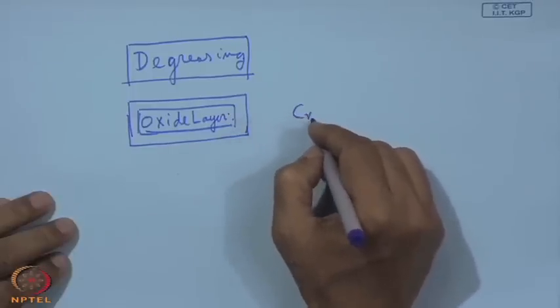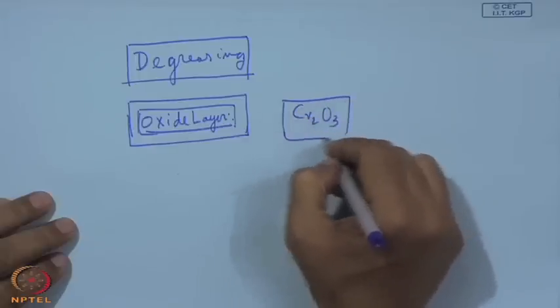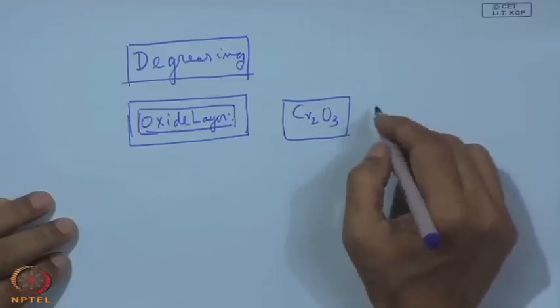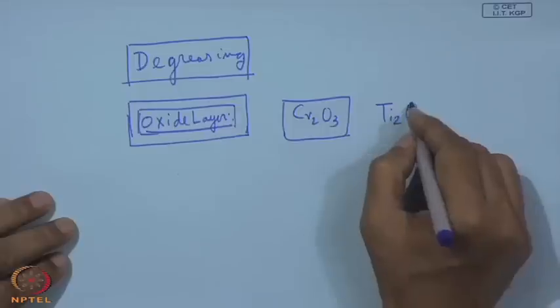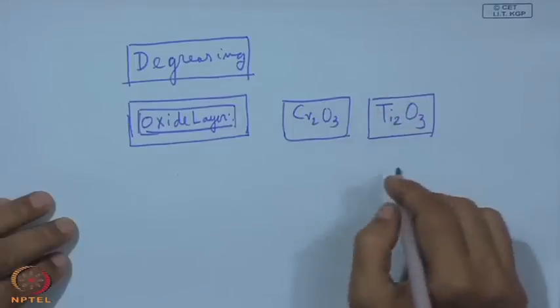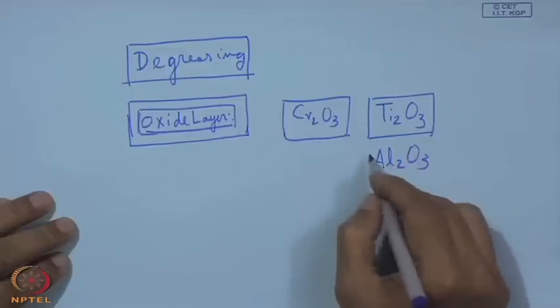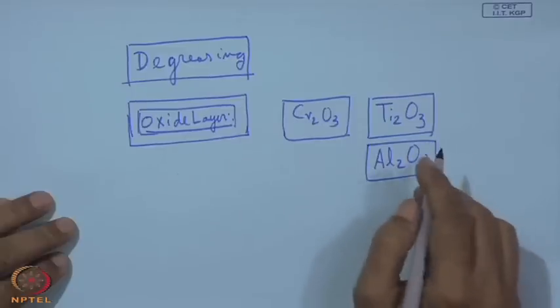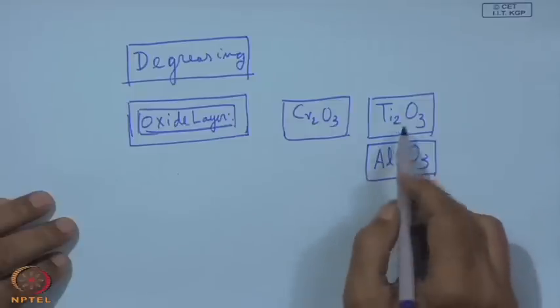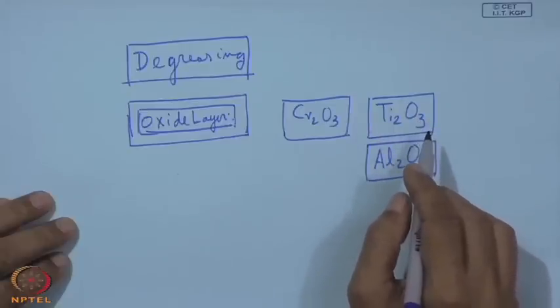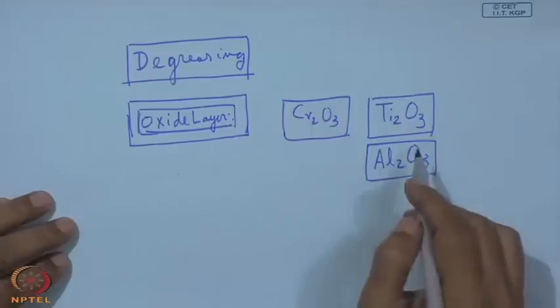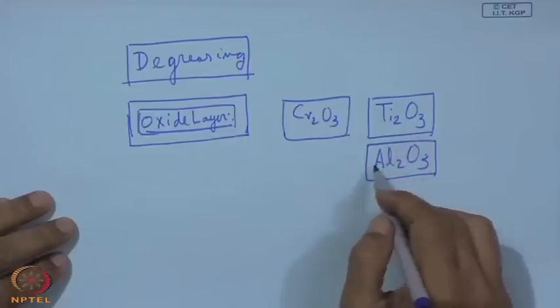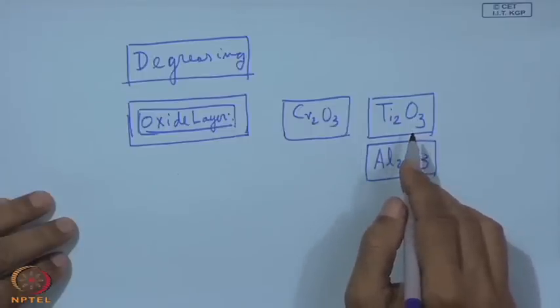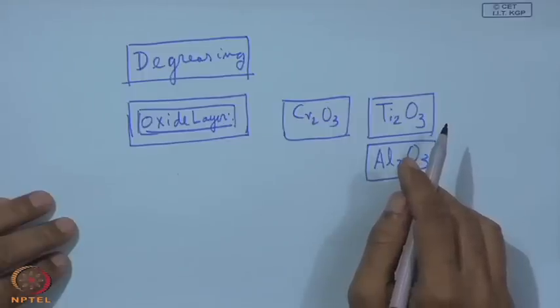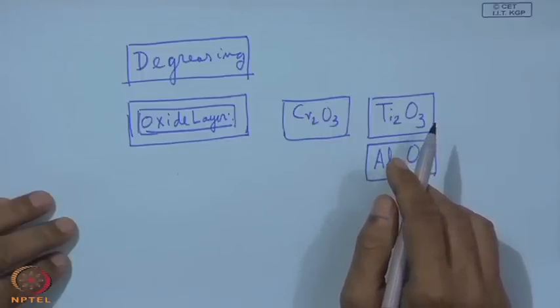On the stainless steel, it is Cr2O3, for example, and then deposition will be extremely difficult. Say if we have some titanium alloys, it can also be Ti2O3. If it contains aluminium, then also it can be Al2O3. If this is present at some atomic level, then this will become a non-wetting surface and we will end up with this globule formation. However, in certain cases, these oxides are not continuously formed, so they are partially ruptured, and that is why it is also possible to have some kind of galvanic deposition even on these two surfaces.